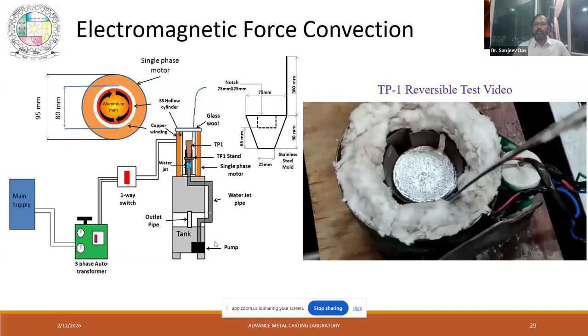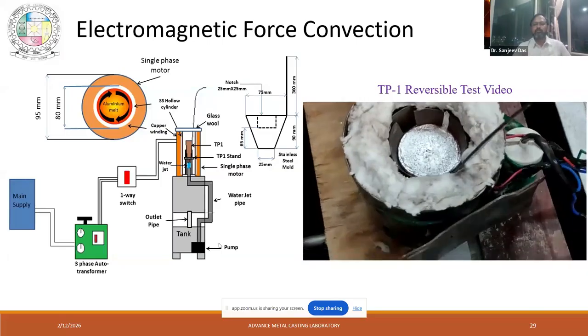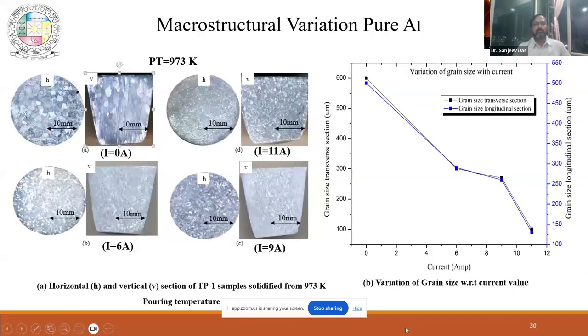So based on this result, let us see what we get. For the microstructure, we take the section, and in the top section you see there is a certain amount of refinement. Now if we quantify it, we see that the grain size decreases with the current. Current means, if you give higher current, you get more magnetic field, right? So as you increase the current, the grain size is decreasing.